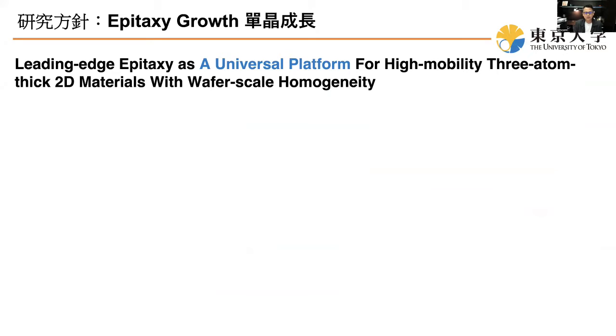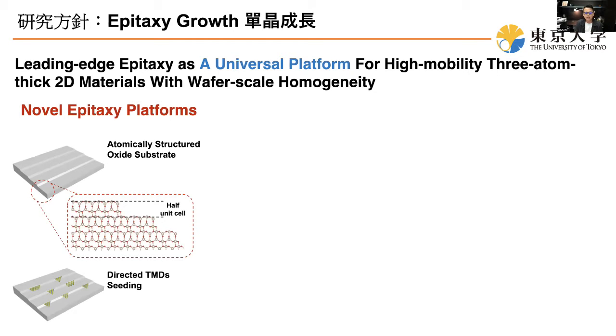The first direction we are working on is epitaxy growth. We specialize in leading edge epitaxy, especially creating a universal platform, meaning that utilizing one platform, we are able to synthesize all types of materials. These materials will be high mobility, probably 1 to 3 atoms thick, and with wafer scale homogeneity. Our approach is that we take a normal oxide substrate and we structure the surface. We found that by structuring the surface into only half unit cell thick steps, we are able to utilize these steps to direct the growth of the materials. Ultimately, they will form single crystal and densely aligned materials.